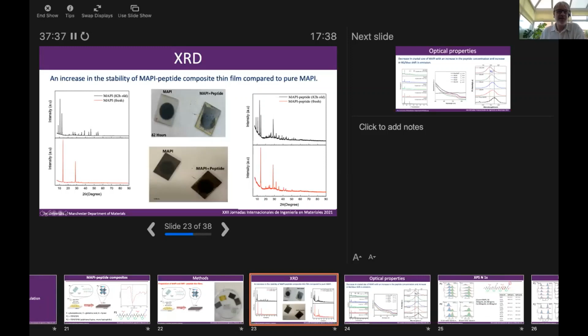So the XRD patterns here, this is for the pure MAPI. We have strong signals associated with the methylammonium lead iodide. When we mix with the peptide, we also see the methylammonium lead iodide, but these other structures are due partly to the peptide gel and partly due to the ITO substrates. We can also see these weak peaks due to the ITO substrates here. When we aged them, the pure MAPI has just disappeared almost completely. It's slightly yellowed because we've presumably formed lead iodide. We then see... Oh, no, we don't. These are all lead iodide peaks now that we're seeing here, and some substrate.